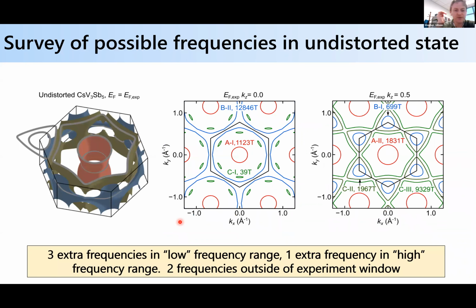One of the things we tried to do was identify what frequencies are coming from what. The Fermi surface is pretty complicated. There's a lot of bands. So what we first did was look at the undistorted Fermi surface, the high temperature state. And Sam Teicher did some very beautiful analysis of calculating what the extremal orbits would be, which occur in the k=0 and k=½ plane. So if you just do an analysis of the extremal orbits that we would be sensitive to in the quantum oscillation measurements,